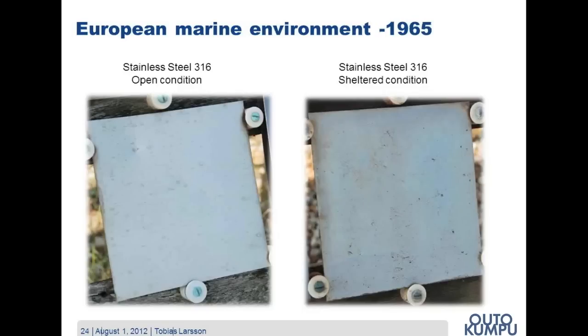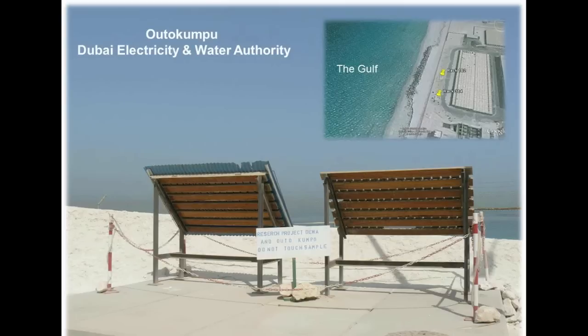If we then look at the austenitic grade 316, which has been exposed for almost 50 years, it still looks pretty good except for some small staining. You can also see from this picture that the sample in the open condition performs a bit better than the one in a sheltered condition. And the reason for that is that in Europe we have the rain that naturally cleans the material.